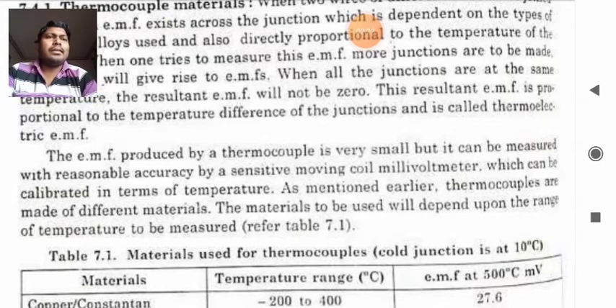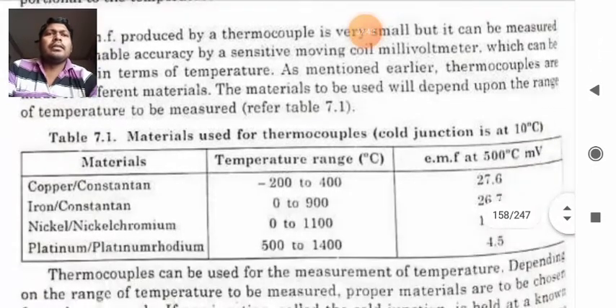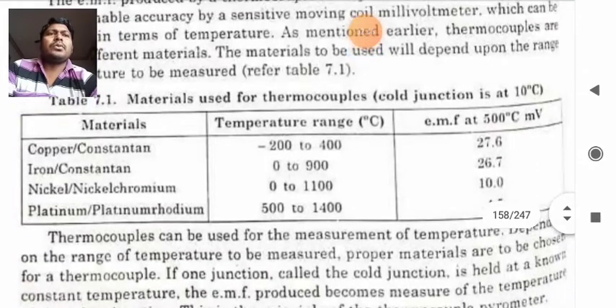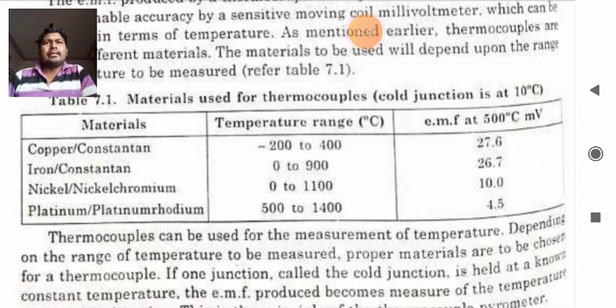As mentioned earlier, thermocouples are made of different materials. The materials to be used will depend upon the range of temperature to be measured. Now there is a table on your screen which illustrates the materials for thermocouples at a cold junction of about 10 degrees centigrade. So what are the materials? Let us discuss. If it is copper constantan, then the temperature range will be minus 200 to 400, and the EMF generated will be 27.6 millivolt.